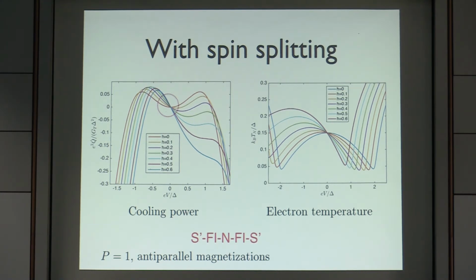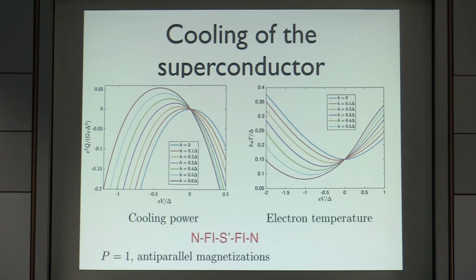Okay. Now, since you have this linear effect, the difference in this case is that you can also cool the superconductor. In the regular case, you always just heat the superconductor. Actually, as you are cooling the normal metal, you are heating the superconductor even more, because you have to dissipate this power somewhere. In this case, you can cool the superconductor. There is a finite cooling power, which is the positive part of this curve in the presence of the spin splitting field, which means you can cool the superconductor somewhat below the starting temperature. In the case of aluminum, this would correspond to starting at 300 millikelvin and going below 200 millikelvin in superconductor temperature. Okay, that's the cooling.